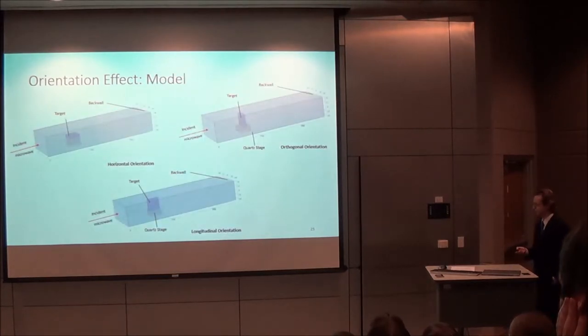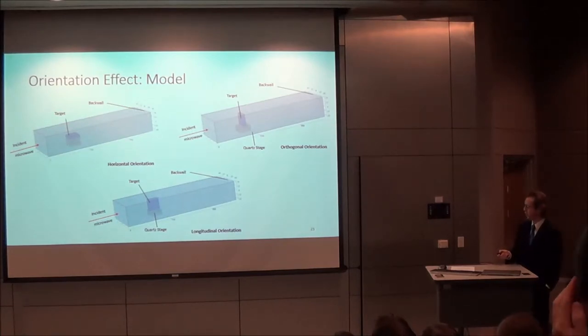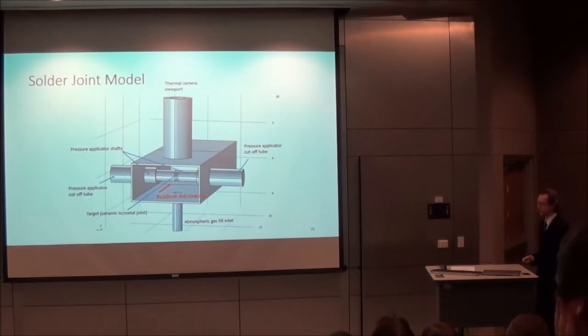And so this is the geometry of the different configurations, the numerical model for studying the orientation effect. Here you have the dielectric target horizontally situated, and then two vertical arrangements, one that is orthogonal to the wave, perpendicular to the wave, and one that is longitudinally situated in the waveguide. So these are the designations I've given to those. This is the model for studying and predicting the solder joint and the heat generation at the interlayer, the base materials and the interlayer between. This is the model of the prototype used for joining, and that will be explained in more detail later.